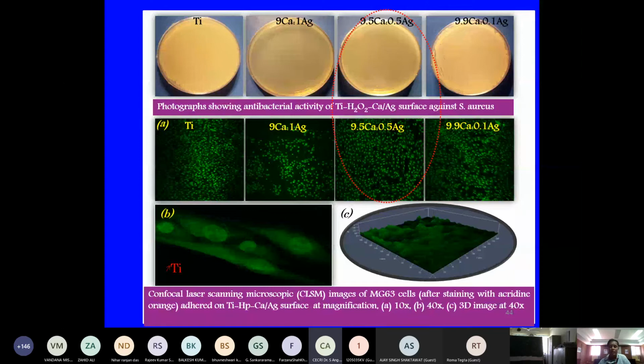And you can see, we try to optimize the concentration of calcium and the silver on the surface, and there is no bacteria, all bacteria are dead. But you can see the titanium sample is not having antibacterial activity, and bacteria have grown on the surface. When we incorporate the silver, in the middle two samples, there is no bacteria. But when you decrease the concentration of silver, then you again find the bacteria. So interestingly, that's why we optimize the silver and calcium concentration, so that it has antibacterial activity as well as bioactivity and biocompatibility.